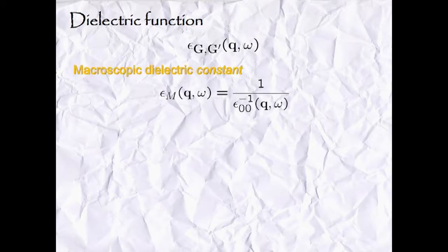Well, one more thing, this is on the microscopic scale. This is how we compute it microscopically, but what is finally measured is the macroscopic dielectric function, which is the inverse of the inverted tensor, and here we take the 0, 0 component. But still, we have the omega dependence here, we have the q dependence here, and the q, as I said, this is the momentum transfer.